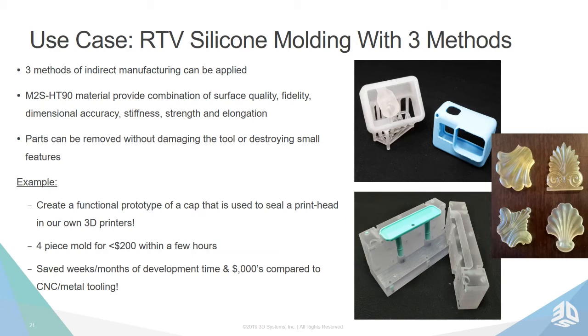In this example, in the bottom photograph here, we actually created a functional prototype of a rubber cap that is used to seal one of our own print heads in one of our own 3D printers. So in this case, a 4-piece mold was printed for around $200, and it was delivered overnight. And this process enabled our own R&D team to trial a true elastomeric part in the machine, and then to tweak the design repeatedly until the rubber injected part was a perfect design for the printer itself. So this process, of course, we're using it to create our own 3D printer, but it saved us weeks, maybe even months of development time, and of course thousands of dollars compared to CNC or metal tooling those tools.